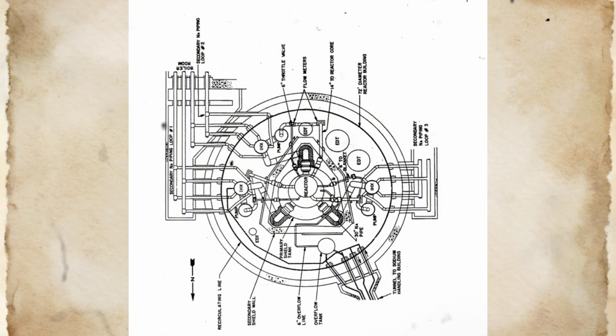The molten fuel that had been released from failed fuel pins had introduced materials into the coolant system that could potentially affect pump operation, heat exchanger performance, or the chemical balance of the sodium coolant. Radiation monitoring throughout the reactor facility indicated that significant quantities of fission products had been released into the sodium coolant system, but the chemical form, distribution, and transport behavior of these materials within the circulating coolant was not immediately determinable through available monitoring systems. Some fission products remained dissolved in the sodium coolant and were transported throughout the primary circulation loop, while others might precipitate onto system surfaces or accumulate in regions of low coolant velocity, such as heat exchanger tubes or piping dead legs.